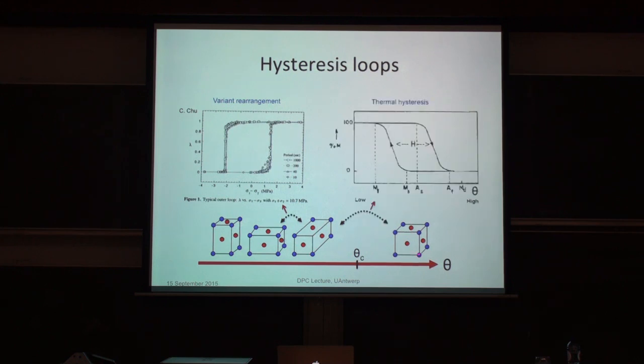Or you can do the phase transformation between the cubic phase and this tetragonal phase by changing temperature. And again, this is percent of the martensite versus temperature. If you're cooling, you begin to transform here, and you finish transforming there. But the other way, you don't transform here. You transform at this higher temperature. First, you transform to the austenite, and then you finish the austenite transformation here. As I say, this phase is often called austenite. And people fit that curve with a parallelogram and therefore define those four temperatures, and they characterize the hysteresis by this.